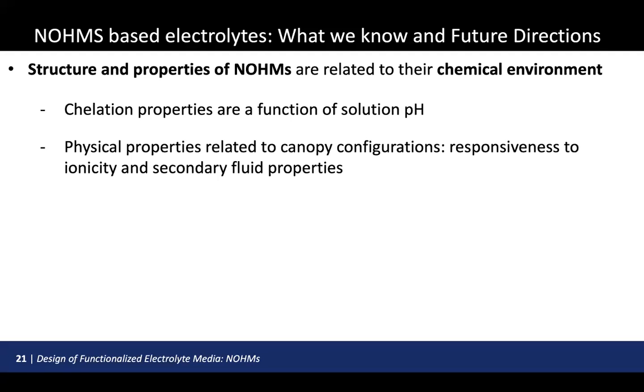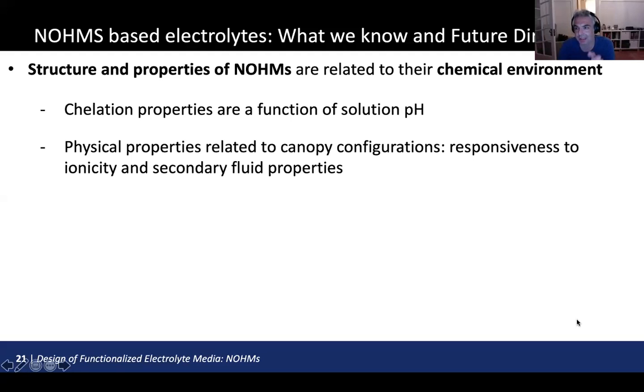So then at what point, right? Because I think you have enough information now to make an estimate on potential energy density improvement or decline. Yeah. So I did kind of a mental experiment, I guess. With the current system that I showed of the copper being tethered onto the amines, if we use 100% NOHMs in solution, which is unrealistic for other purposes, the effective molarity of that mixture is about 8 molar copper. But again, with all these limitations, we can't really have 100% NOHMs as an electrolyte.